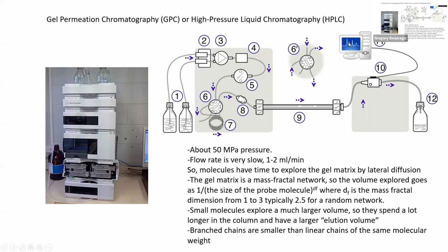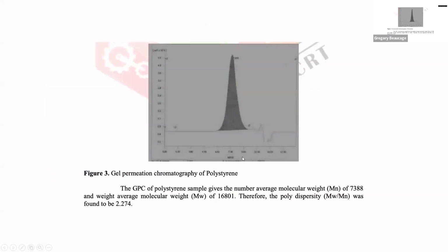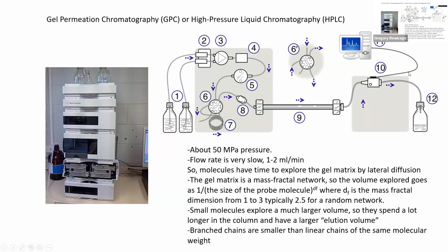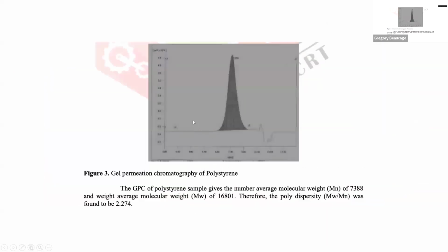Basically it's going through so slowly that it's thermally diffusing laterally. The small things explore a lot of the gel forest, and the large polymers zip through just the main paths and come out first. So the first thing you get is big things, and later on you get smaller and smaller things. You'll get a curve like that. If this is retention time down here, sometimes labeled retention volume, large molecular weights are here, small molecular weights there. Then you convert this into a molecular weight distribution using usually a polynomial function. You calibrate this with standards, anionic polymerized polystyrene standards that are monodisperse and just have a single spike. So you get a time versus molecular weight, do a polynomial fit, and then you can convert whatever retention time to molecular weight.